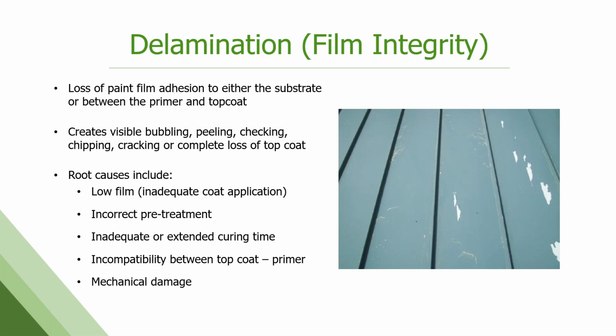inadequate curing on the coil line. Maybe you had a formulation incompatibility between primer and top coat, that can happen. And then the other big one is mechanical damage. So scratches: you can see in this picture, there's a vertical scratch or line next to each section that's peeling. That was scratches that occurred during installation. Now you have an opening in the coating, and over time, water and ice and other stuff gets in there, and you start getting that paint peeling back from that scratch line.